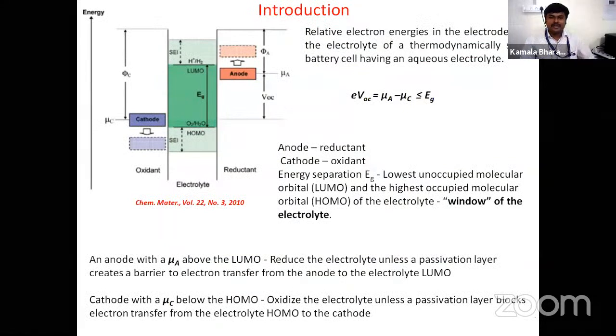Okay, so this is the band diagram of a complete battery with a liquid electrolyte. Open circuit voltage of a battery is basically decided by the chemical potential of anode and cathode.